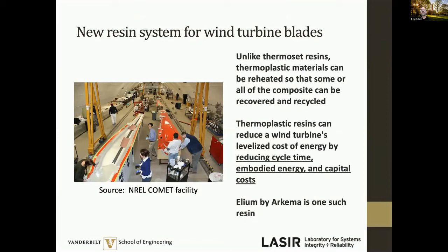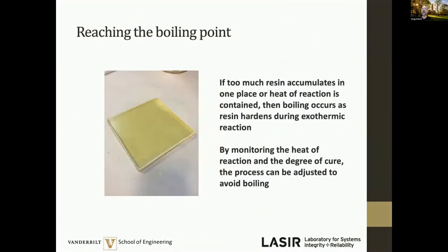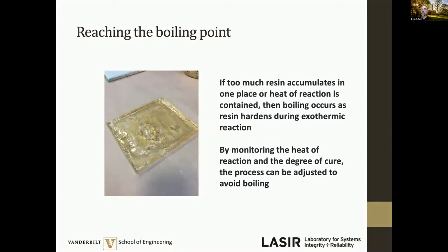And our role in this project was to try to assess the thermal state of this resin as it cured, and specifically to try to avoid boiling of the resin. And so, for instance, if you cure out a block, a plate of this resin, and you do it properly, this is what it looks like. If you cure it out and it boils, this is what it looks like. Okay, so you get that porosity as the gas is released during boiling. So what we would like to try to do is utilize the heat signature of the curing material in order to ascertain if it's produced flaws in the manufacturing process.